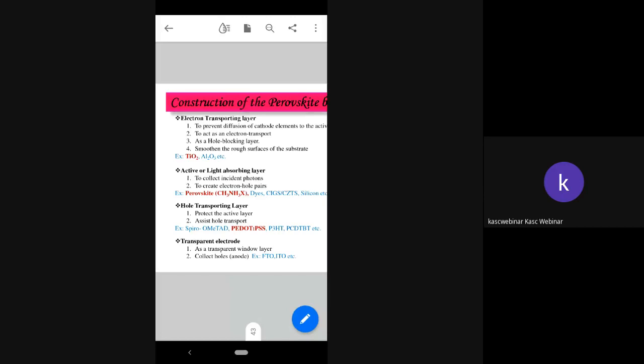And next one is the light absorbing layer. The light absorbing layer is used to collect incident photons and to create electron hole pairs. Example for this layer is perovskite materials. For this, we can use CH3NH3X. That X may differ. Whichever element we are interested in, we can replace that X with that particular element and check the efficiency. Or else we can also use dye molecules. And the third one is hole transporting layer. Hole transport layer is used to protect the active layer and to assist hole transport. Example for this is P3HT, PEDOT:PSS. And the last one is a transparent electrode. This acts as a transparent window layer and collects holes. Example for this is FTO and ITO, the well-known materials.